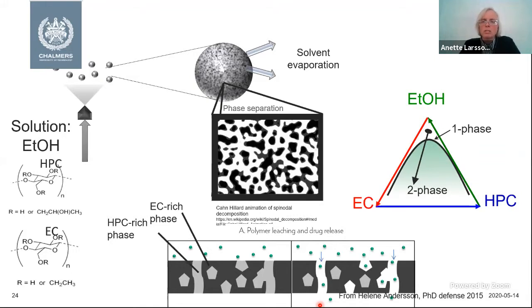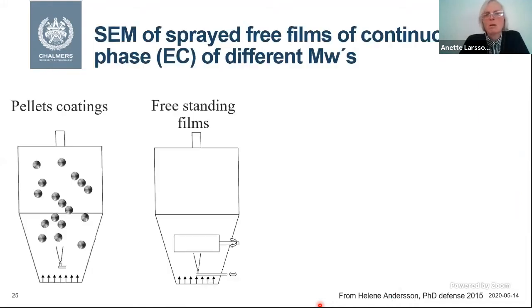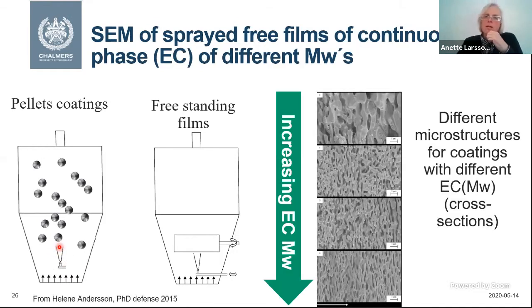Another thing when you change the molecular weight is also that you lock the system at different positions. So we tested this using two different ways of making the coatings. Here we made free films. So we had a rotating drum, and here was a traditional fluidized bed where we coated the pellets. And here is the molecular weight that changes. And here are the cross sections.